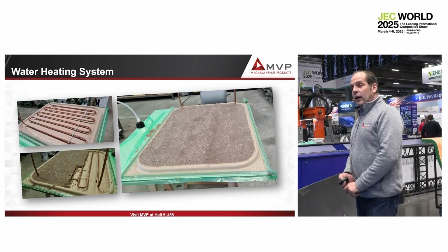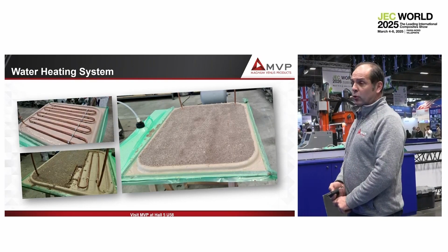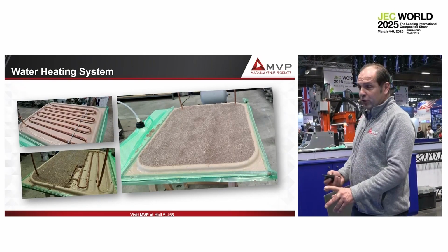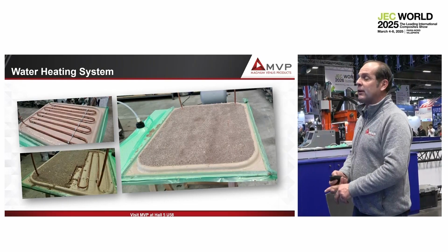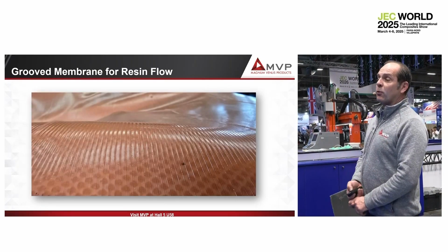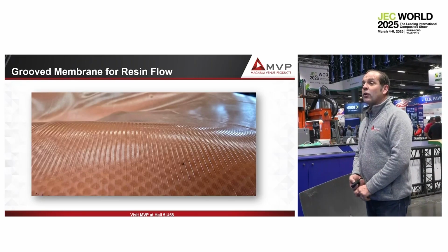Then, as we work with epoxy, we have to heat the mold to work on temperature, so we have developed a system which is not new, but we just actualized it, which is a mix of resin and sand around the copper pipe. So this is a silicone bag.